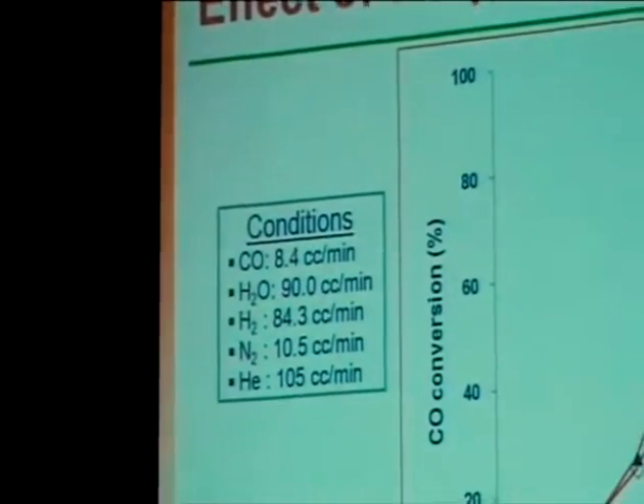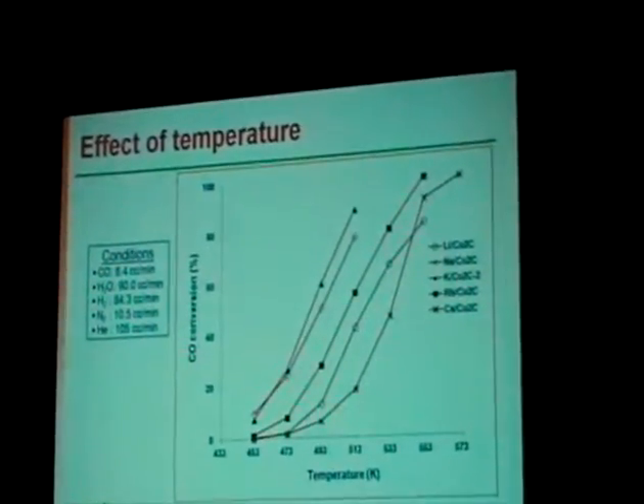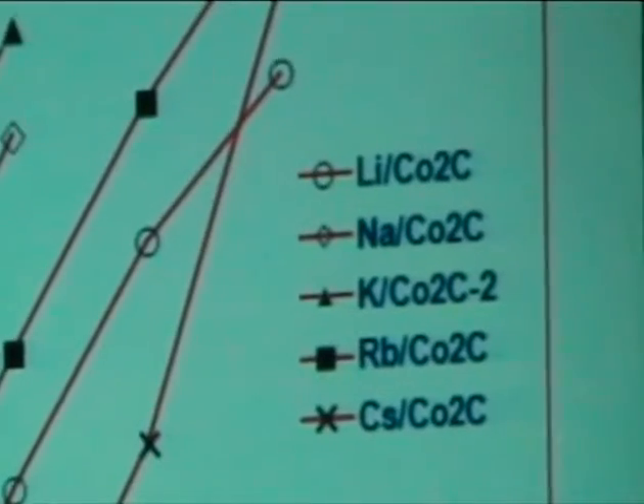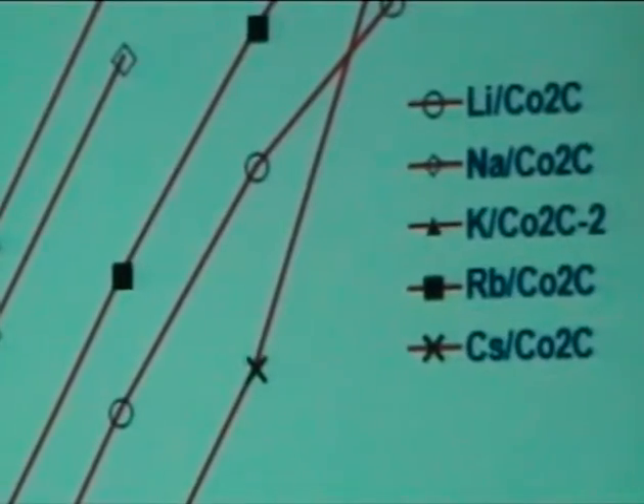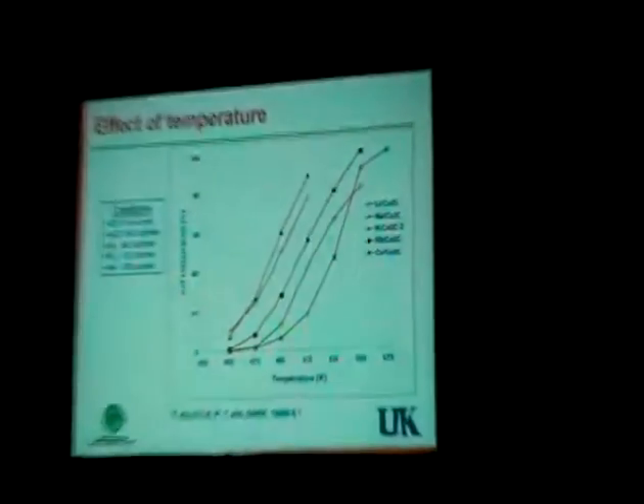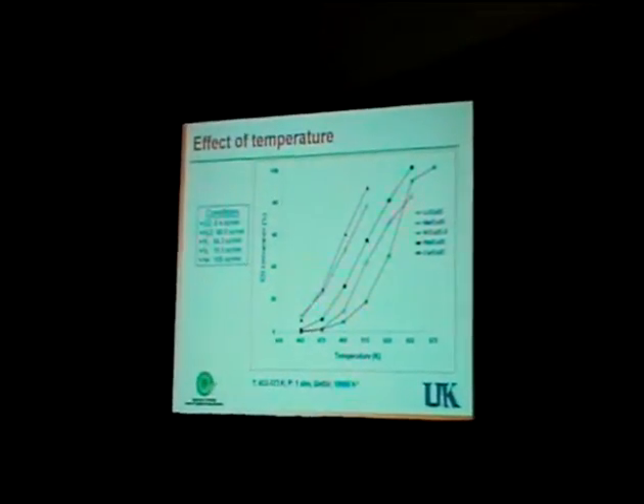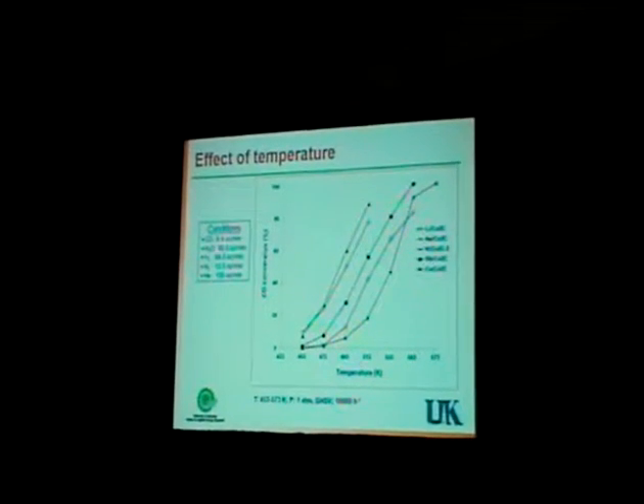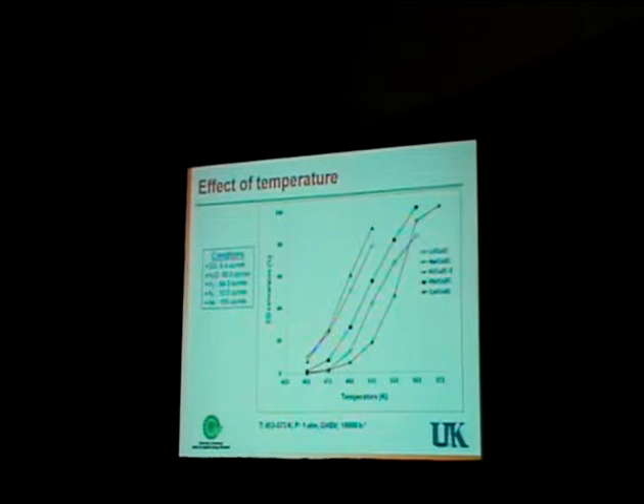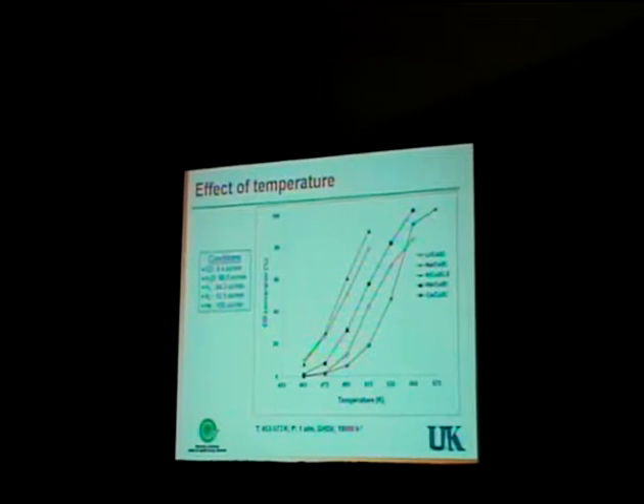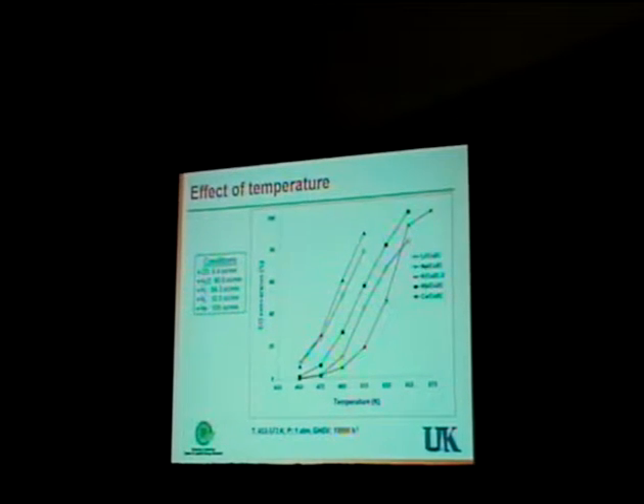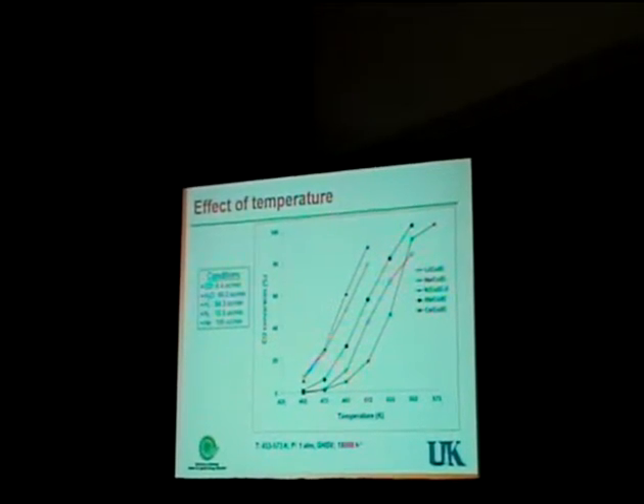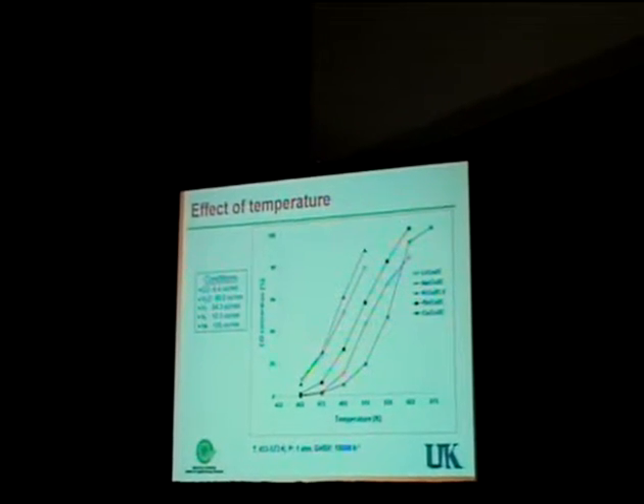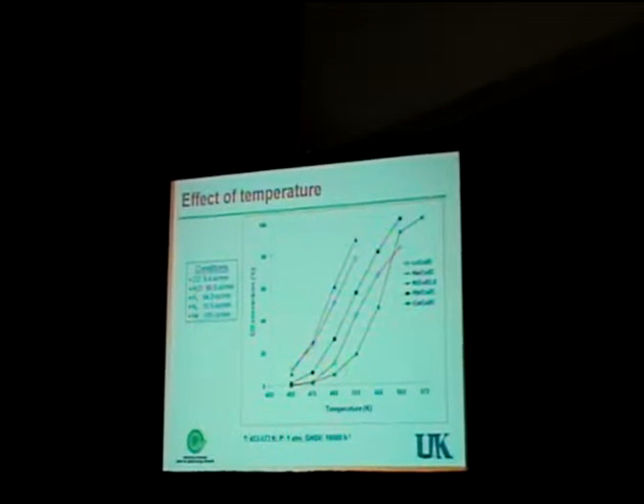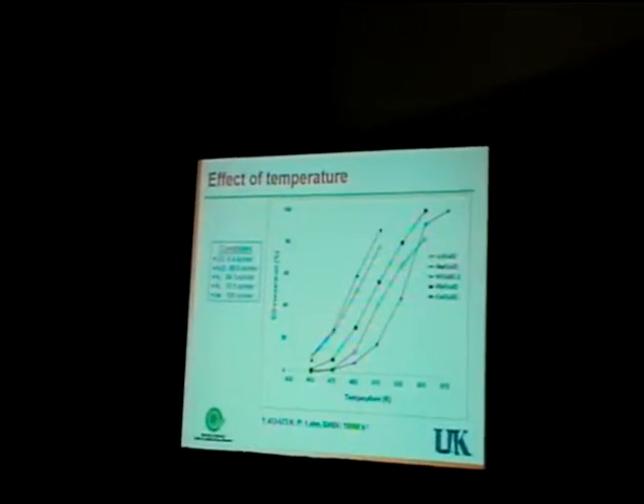So we studied the effect of temperature on the water gas shift of the various catalysts. And we are comparing here the temperature effect on the lithium, for example. The lithium shows a much lower activity even if you increase the temperature from 450 to 550. Sodium and potassium exhibit higher activity compared to the other promoted catalysts. In the next slide, I'll show the unpromoted one. And here we are comparing the effect of the alkali. Rubidium and cesium again are dropping, which could be because the accumulated surface carbon influences this activity difference.